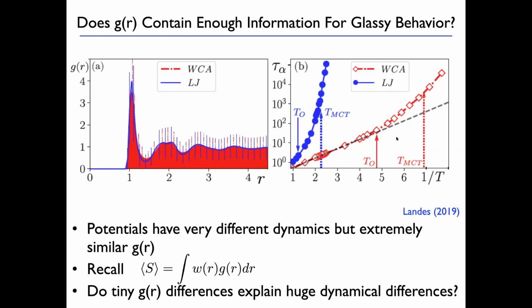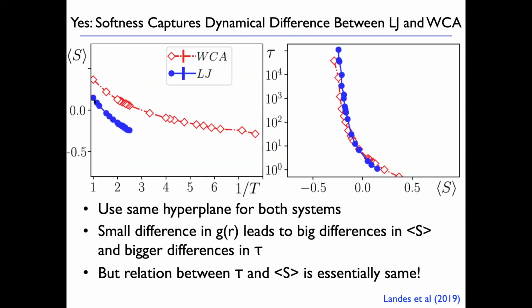So is that enough? Well, remember that softness is this weighted integral over the correlation function. So the average softness is a weighted integral of the average pair correlation function, and this is a tiny difference, comparable to the tiny difference we see between particles with positive softness and the average. So here is the average softness. And what you see is that the average softness is definitely different for the two systems. The red system was with only repulsions, and the blue system is the Lennard-Jones. But the relaxation times, which were so different as a function of 1 over temperature, are nearly on top of each other when I look at them as a function of the average softness.